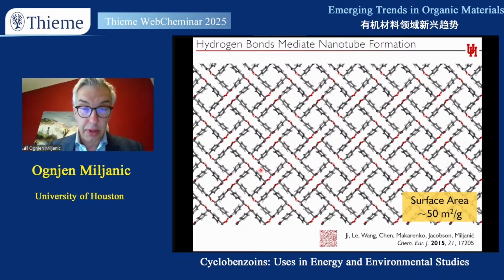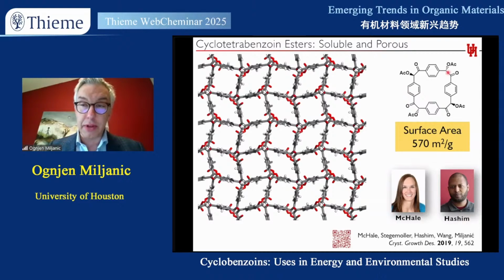And we did that through what we thought at the time was a trivial modification, where we take a secondary alcohol and we convert it into this acetate ester. And one result was expected, and that is the solubility of this material has increased dramatically, so it is soluble in most organic solvents now. But also its surface area has increased dramatically, more than 10 times. And this is because we now open up secondary pores in this molecule.